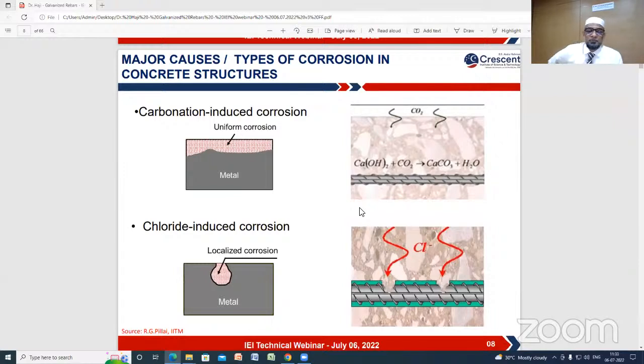There are two aspects which are very important in terms of corrosion control or prevention in steel rebars. One is carbonation, and the second one is chloride. Most of the participants are students, so very simply, carbonation means carbon dioxide intrusion. Chloride intrusion, naturally, we know. The carbon dioxide in the dry season will go and occupy the pores of the concrete. During the rainy season, it combines with water and is converted into carbonic acid. This carbonic acid has the tendency to reduce the pH of the concrete. The original pH of the concrete is 12 to 13. Once the pH is reduced to 9, the concrete no longer protects the steel, and steel corrosion will accelerate and lead to distress. In the case of carbonation, the corrosion over the steel rebar is uniform corrosion.